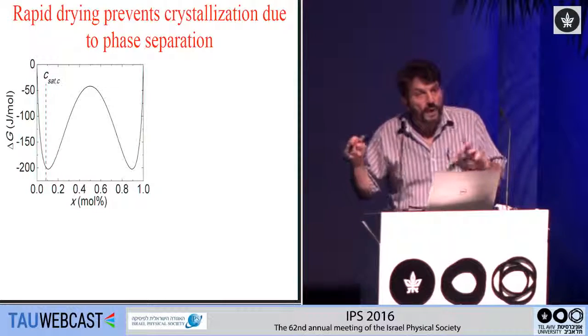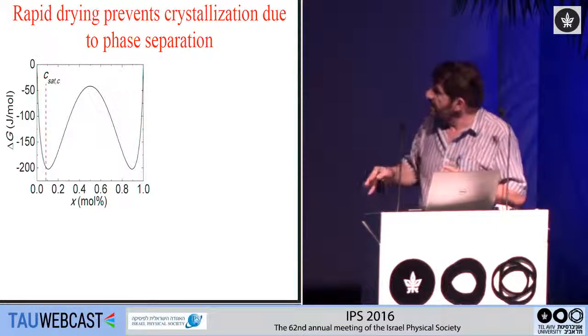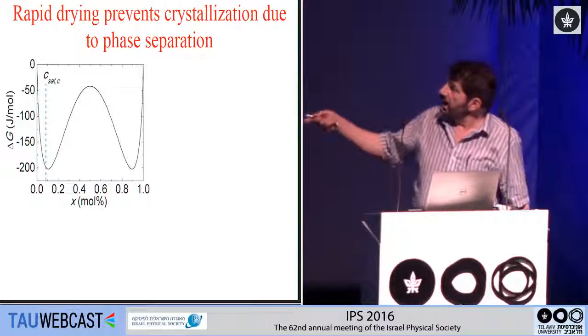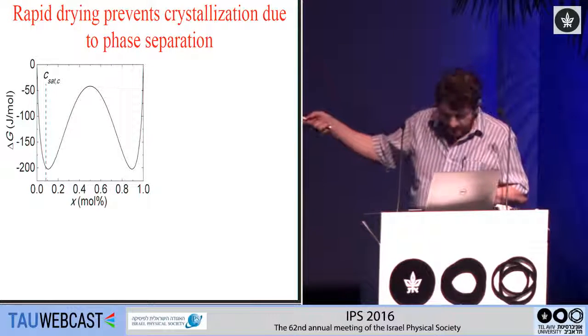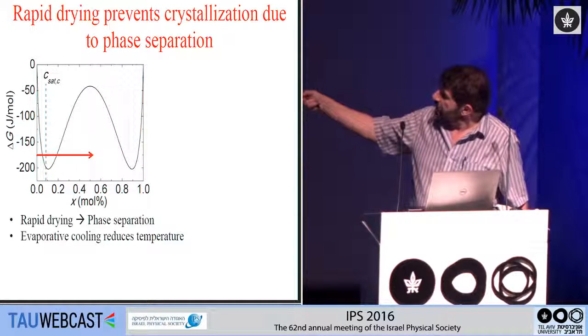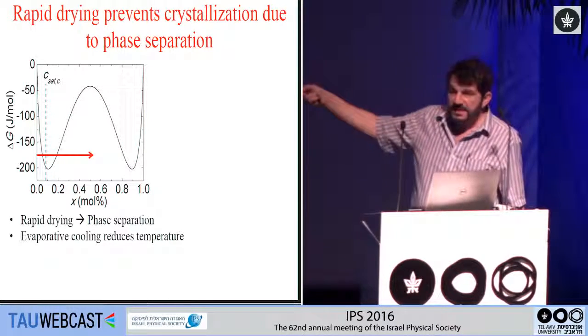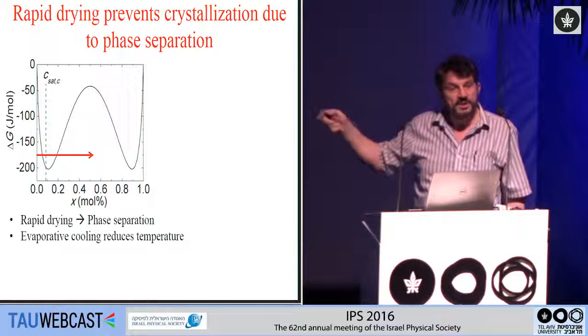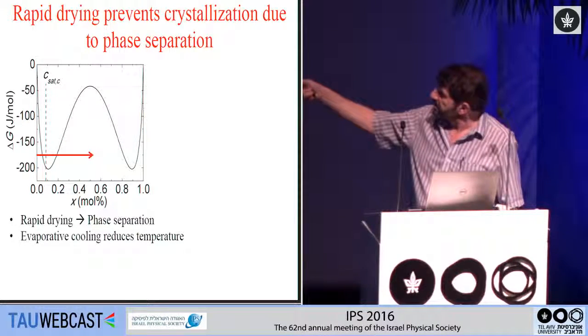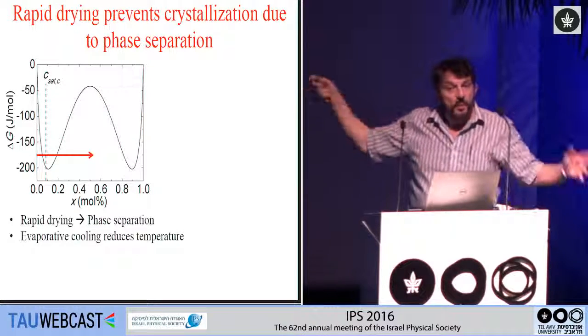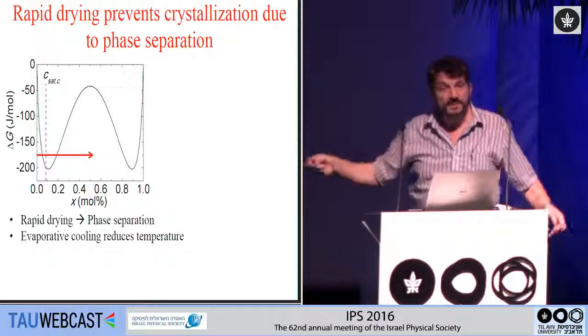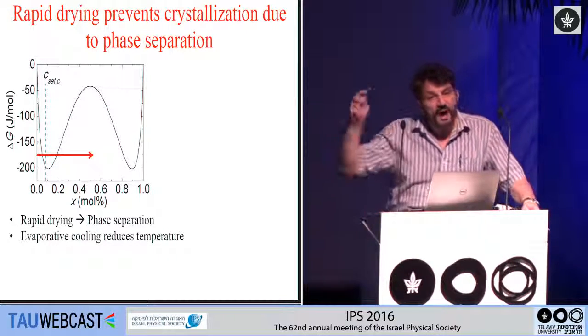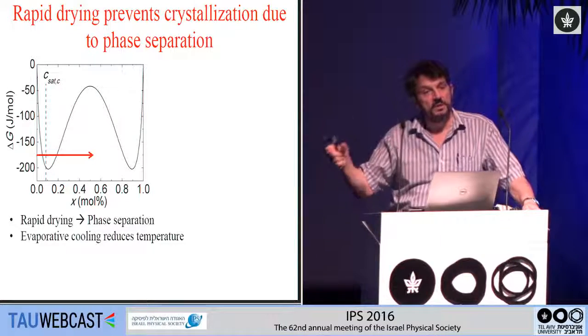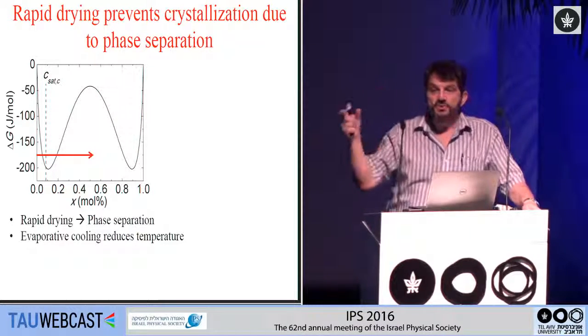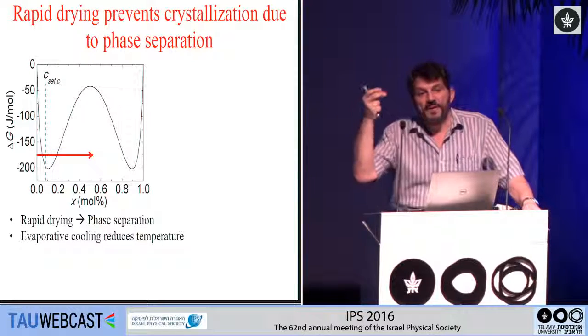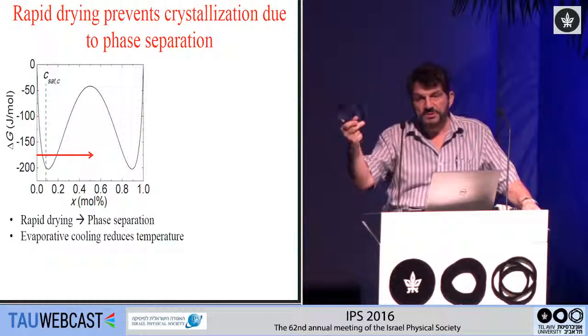So what's happening? Well, always when you have a system that wants to crystallize, as you change the concentration, it's going to undergo spinodal decomposition. So if you increase the concentration to the point where it crystallizes, it's going to phase separate. Before it crystallizes, it's going to phase separate due to spinodal decomposition. If you're at this point, it's going to phase separate to something here where it's highly concentrated, and here where it's something that's very low concentration. The high concentration region is very strongly cooled because of evaporative cooling.